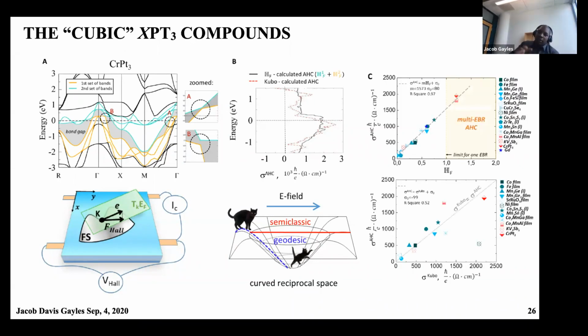Particularly, we like this approach because it has a very good correlation with experiment. Above, you see a list of popular materials: cobalt, iron, manganese 3 germanium, compared to this hyperbolicity factor, which almost shows a 1-to-1 correlation. Whereas when we compare with the anomalous Hall effect in the Kubo, this correlation deviates. We believe this hyperbolicity function actually captures more of the physics than the Kubo in this case.